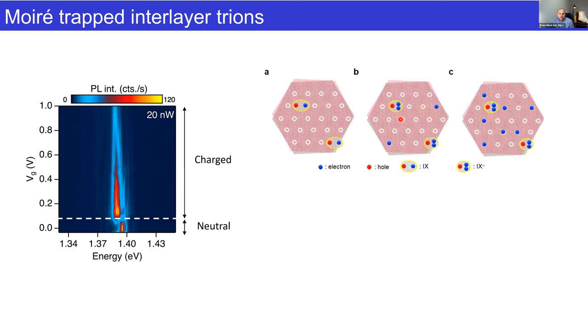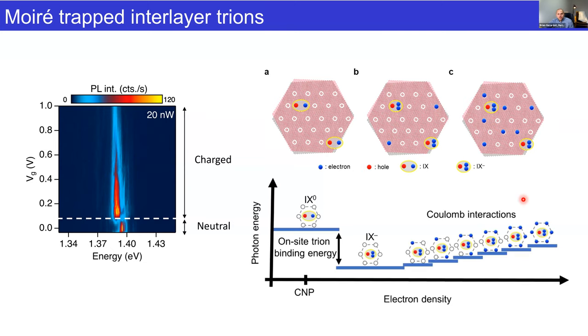The first thing that happens, we can see that the on-site Coulomb interaction energy is negative by about 7 meV. So we expect to capture a single electron. Then as we continue doping, we expect to start filling up some nearest neighbor sites and also some further neighbors in the lattice. As the nearest neighbor sites should have the dominant interaction energy, we can expect a signature that looks something like this. We have a certain energy, then a big jump due to this initial change. Then we expect to see a staircase of Coulomb interactions as we load different carriers into the moiré lattice.